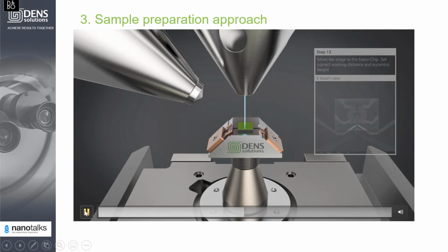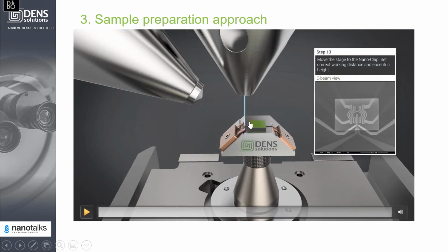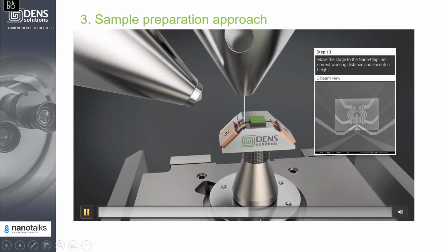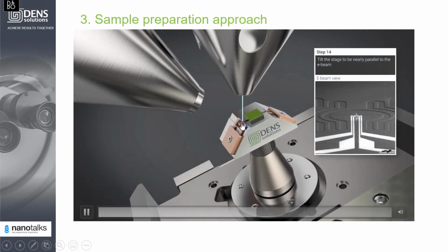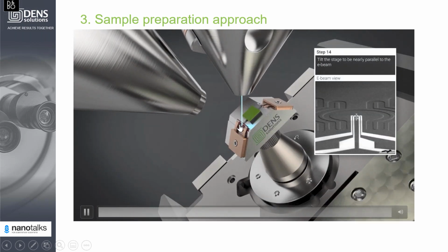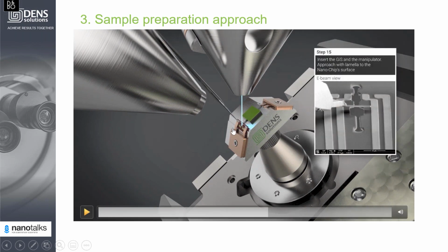So one important part to mention is that the lamella, the Nano-Chip and the sample, their positions, their eccentric height, are very similar, which makes the whole process safer. So in the next step, from the sample, you move to the Nano-Chip. You adjust slightly your eccentric height, and then you tilt nearly parallel to the electron beam. So the next step is to put the manipulator in with the lamella.